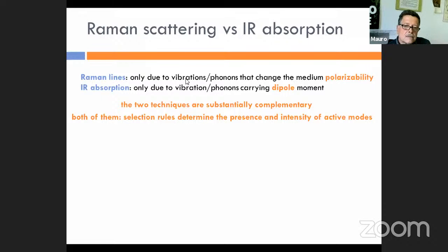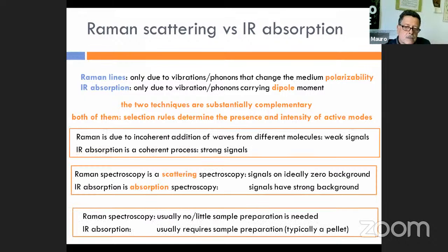So there is a kind of selection rule that distinguishes between vibrations which are Raman or infrared active. And what happens is that the two techniques are rather complementary, and both of them have their utility in spectroscopy. Some more differences are due to the fact that Raman is due to incoherent addition of waves. So the signals generated by the matter are rather weak because they are a composition of incoherent contributions. Instead, IR absorption is a coherent process. Photons are absorbed coherently by the material, so IR absorption produces strong signals.